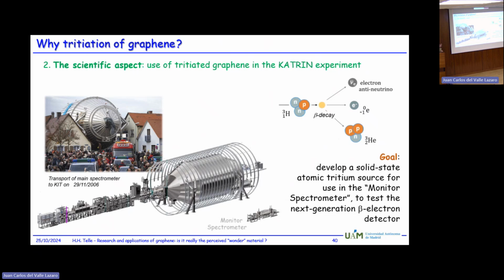But there are two caveats here. One is it's not connected to the tritium circulation. And the second thing is that you do not want to contaminate your complete system with a flowing gas through it. So here comes the graphene into place. You bond tritium to it, so you have it in solid form, so you can put it in, take it out, and no contamination left in the system itself.